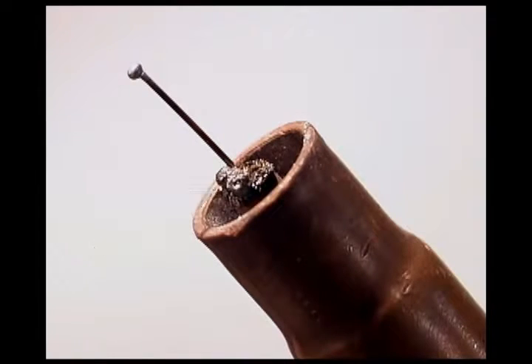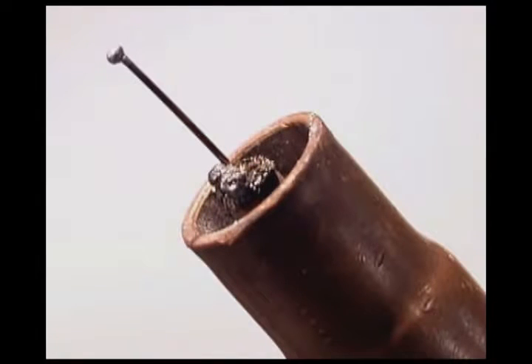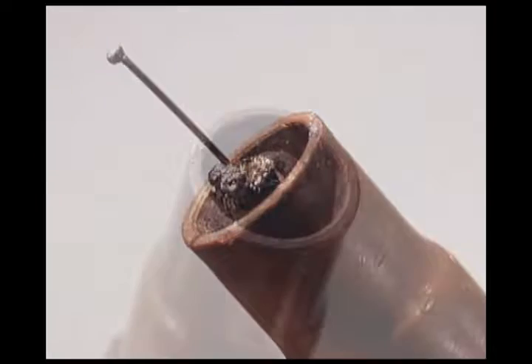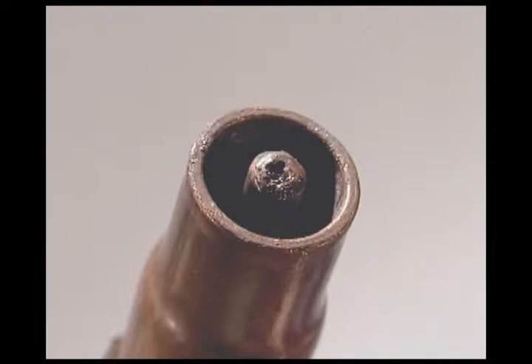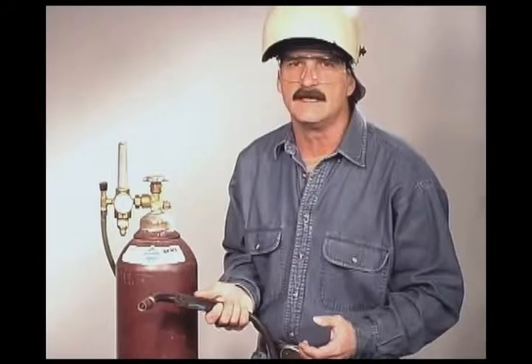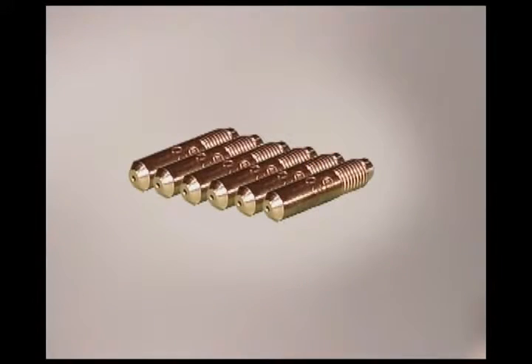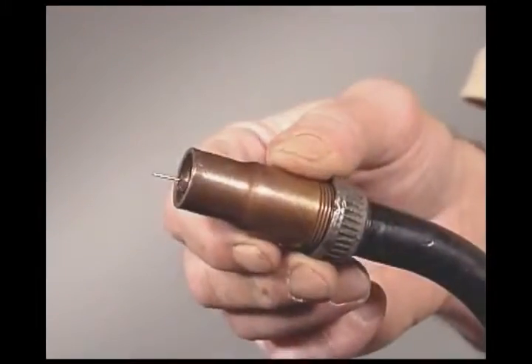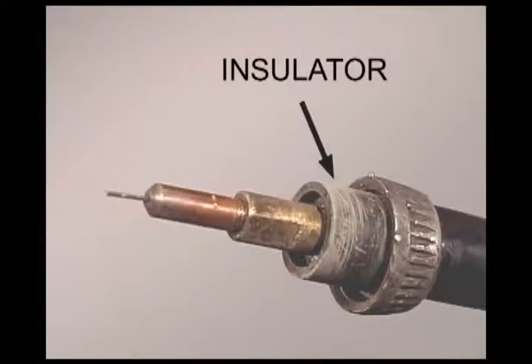If that heats up, it expands and pinches the wire, causing it to feed erratically. The wire can also burn back, sticking at the tip. This generally happens when you're starting the arc, especially if you're in an awkward position or the metal isn't clean. It's a good idea to keep a few extra contact tips on hand. The nozzle will either push on or screw on, but it needs to fit snugly. If it loosens up, you may have to replace the insulator.